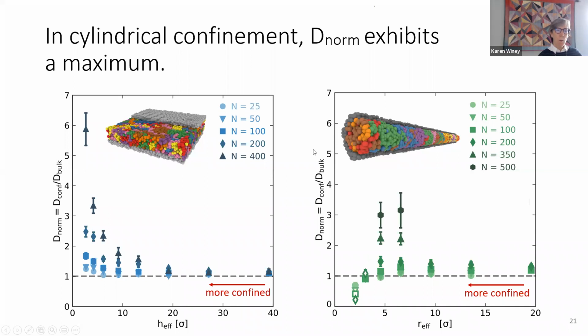Again, this is the normalized diffusion coefficient: diffusion in the confined system normalized by the bulk, as a function of the radius of the pore. As you get more confined, it's increasing. It's hard to see all the different shapes, but sometimes it increases a lot, and if it's 500, it increases just a little bit. But then there's the surprise: it rolls over and gets slower. The increase in diffusion coefficient we can understand because it's disentangling. Disentangled chains diffuse faster. But this rolling over was a puzzle